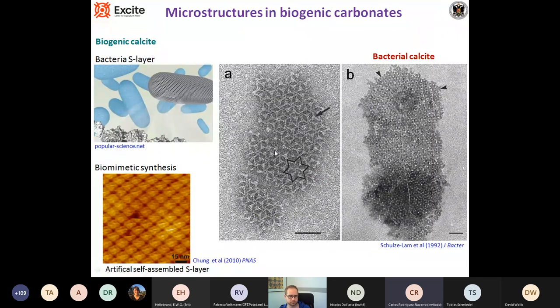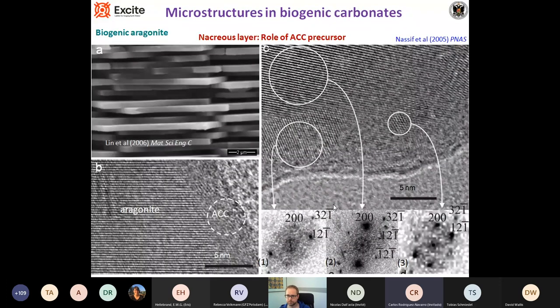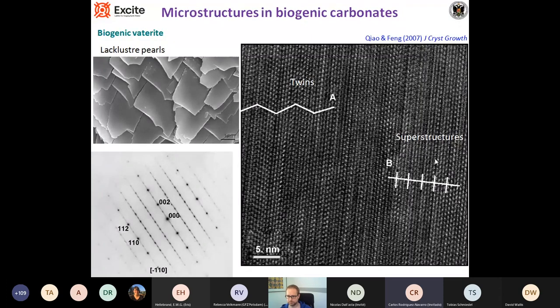In the case of bacteria, they have an S-layer and a structure that can be mineralized to form a peculiar structure, which we can reproduce in the lab by biomimetic synthesis. In the case of aragonite formed by a brick-and-mortar structure, we can see that the growth of the bricks takes place via an amorphous calcium carbonate that eventually transforms into aragonite — and we can induce that transformation in the TEM using the electron beam, observing the original amorphous phase transforming into aragonite with slightly different orientations in different parts. We can also see modulations and superstructure in the case of biogenic vaterite imitating nacre-like pearl vaterite.